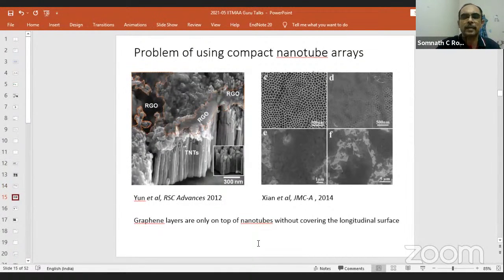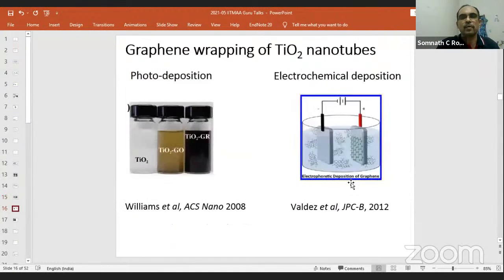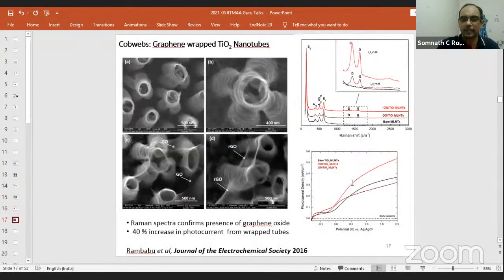Before that, we tried to look up whether people had done this. There were some attempts to wrap individual nanotubes with graphene or graphene oxide layers, but they had failed, because the earlier generation nanotubes were all very, very compact. Whether they call it reduced graphene oxide, since this is not pure carbon only, there are some oxygen or other functional groups. The sheets were all confined to the top of the nanotubes, as you can see here. We said, no, it's not going to work. So what we did, I will first show, then I'll come back to that point: we changed the chemistry of the anodization a little bit.